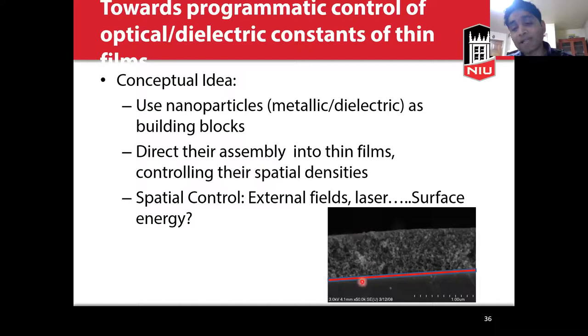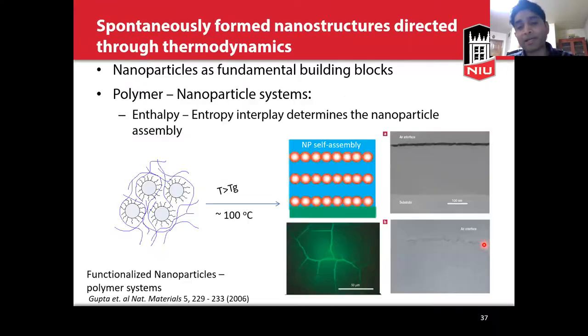So in this example, I would like to use the surface itself, because in the nanoscale, the surface really matters. The interfaces really matter. Can I use the surface of my substrate where I want to deposit these nanoparticles and somehow control the movement of the nanoparticles so that in one region, I have more dense packing of the nanoparticles, whereas in another region, I have more loose packing, so I have more wide spaces, and that way I can control the spatial optical properties of the structure of the film? So that's the idea behind this.